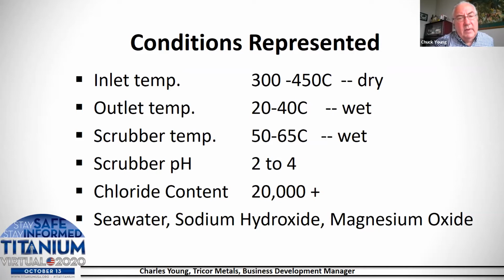in the scrubber. Outlet temperature is normally 20 to 40 degrees C, and it's wet, but you still have scrubber pHs of 2 to 4. And because of the sulfur content in the fuel, this is going to be some sulfuric acid. The chloride content is going to be high because you're using seawater. Plus there's probably some chlorine in the fuel itself, so that you get 20,000, 30,000 chloride levels.